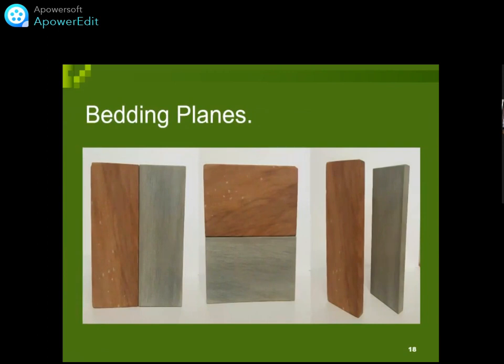As sedimentary stones, which you will primarily deal with in the Scottish central belt in vertical masonry, we're talking about bedding orientation. And I just wanted to show you this. So we looked at that picture of Ballot Mile earlier, where I referred to the natural bedding of the stone, so how it was laid down. So here you can see two versions of the same thing, a red sandstone version and a grey sandstone version. And you can see the natural bedding. So in your walling products and really any products that can be pinned in, you want to keep the orientation of the bedding the same as it was in the quarry. So if you imagine this was two pieces of ashlar or rubble walling, this would be bedded correctly because the weight of the stone is pressing down on these beds as they're built. And these would be the faces that we'd be looking at. And you can see that that will hold this stone in compression and so will stop that stone splitting on this weaker point, which is the bedding.